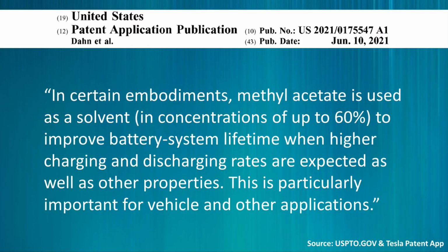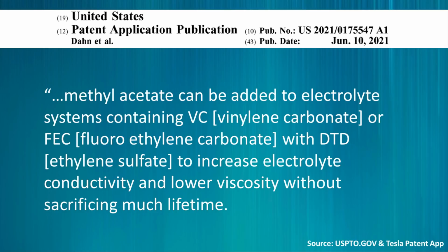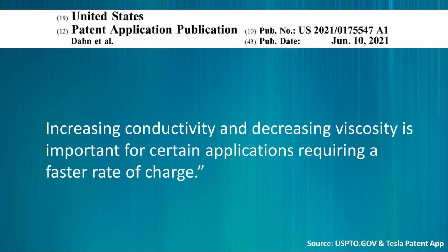Here's how Tesla describes this. In certain embodiments, methyl acetate is used as a solvent in concentrations of up to 60%, to improve battery system lifetime when higher charging and discharging rates are expected, as well as other properties. This is particularly important for vehicle and other applications. Methyl acetate can be added to electrolyte systems containing vinylene carbonate or fluoroethylene carbonate with ethylene sulfate to increase electrolyte conductivity and lower viscosity without sacrificing much lifetime. Increasing conductivity and decreasing viscosity is important for certain applications requiring a faster rate of charge.